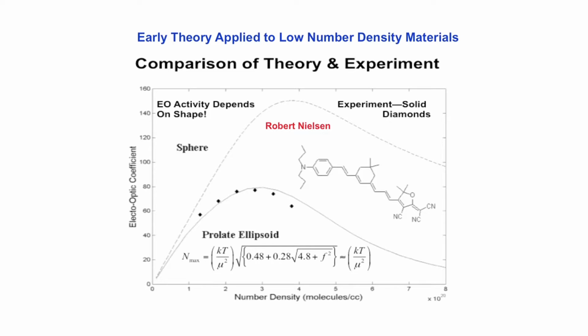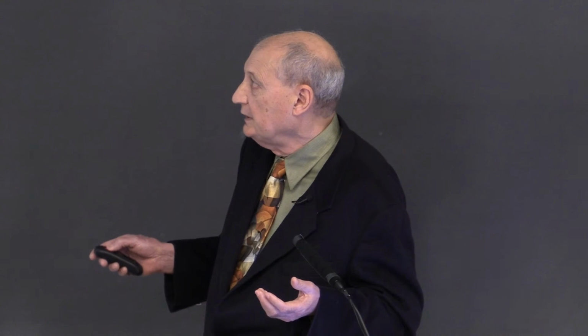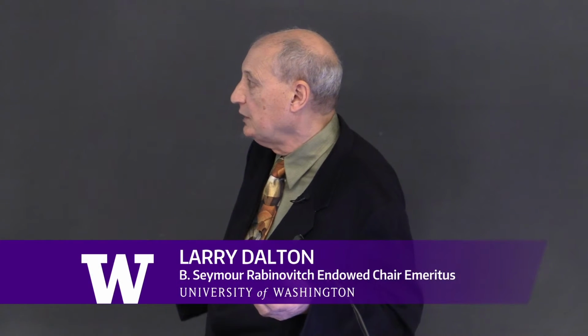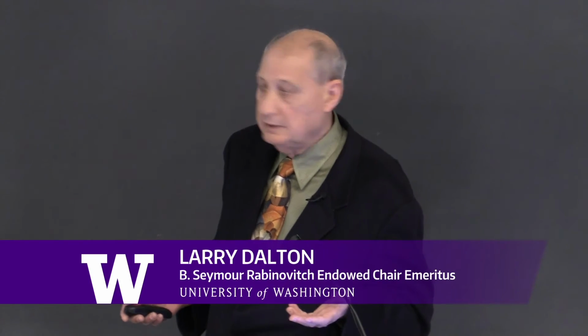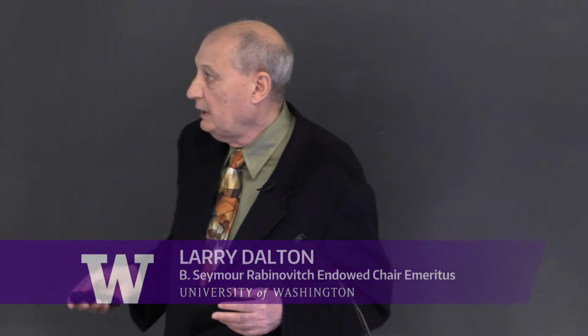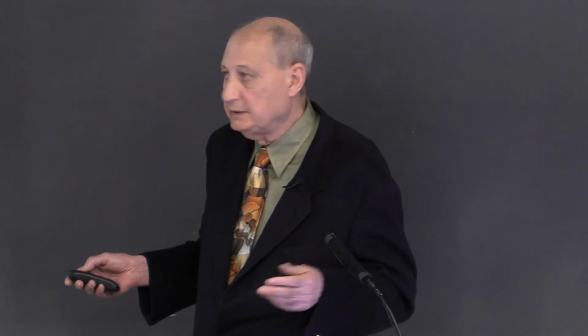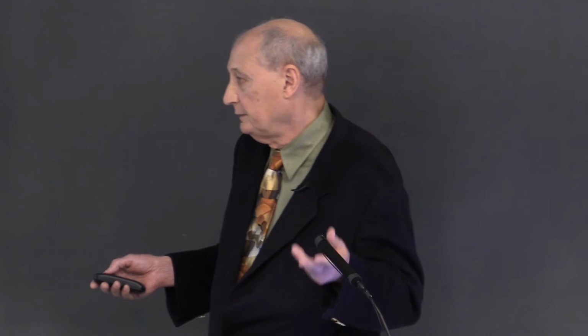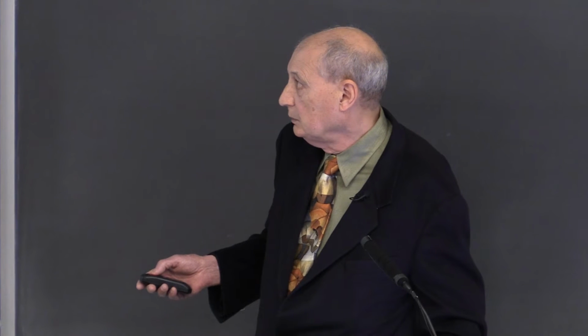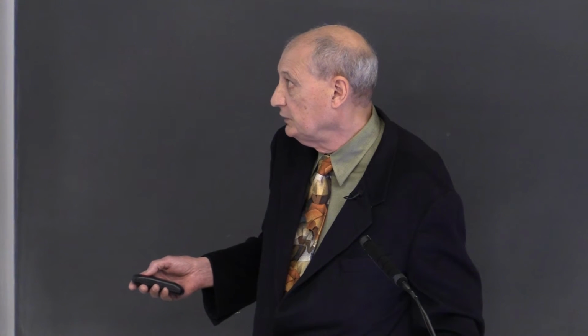And the exact nature of the curve is defined by the shape of the chromophore as well as the dipole-dipole interactions. And of course, shape is defined not only by this pi electron system, but by whatever you hang off these various regions. And so theory says if you can make this into a spherical shaped chromophore, you get dramatically improved electro-optic activity. And this led very quickly to a 2000 Science paper, which received about 1,000 citations and also a great deal of news coverage.